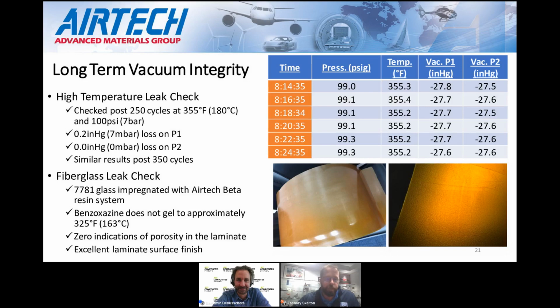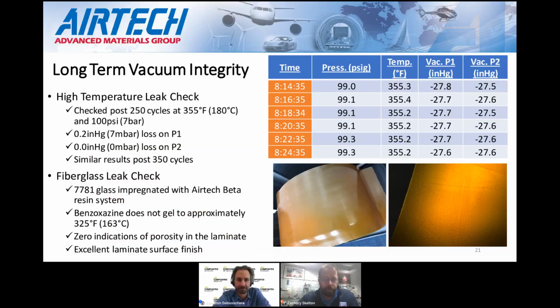So this was off of the cycle test tool. This was post 250 cycles. We are still evaluating it at 350. I can tell you right now the data is identical, but this is just the data post 250. So this is the raw autoclave data, 100 PSI, 355F, so 180C and 7 bar. But you can see the raw autoclave data.